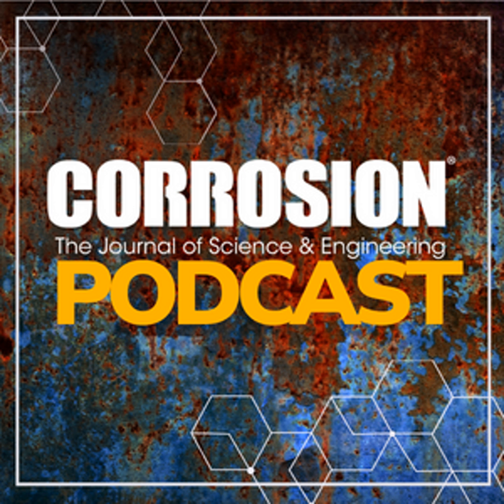Maybe just one comment. First of all, the main goal of the study was to directly identify the OH and chloride containing species. And thanks to the first ToF-SIMS measurements, we observed some strange things, especially at the interface between the oxides and the metallic substrates. That's why we decided to have some 3D imaging of the surface, where we observed the pitting degradation first, and then the more generalized corrosion with time. So it has been done in two steps. First, direct evidence of the different species, and then 3D imaging to have access to surface degradation mechanisms.